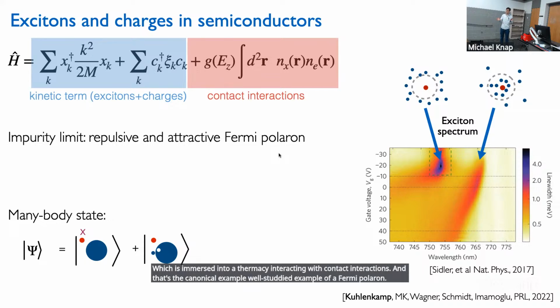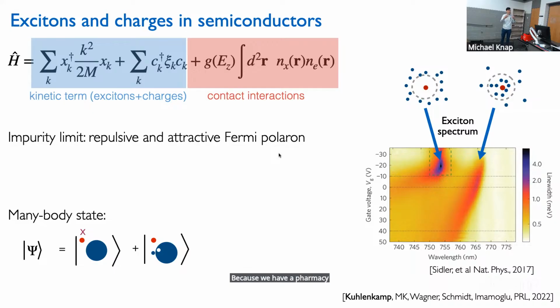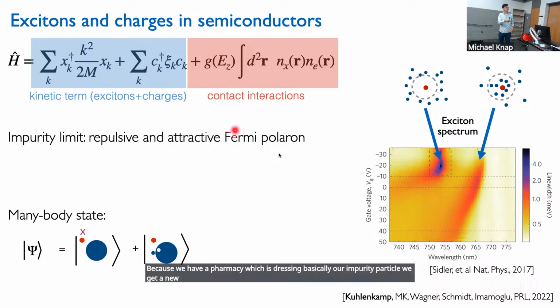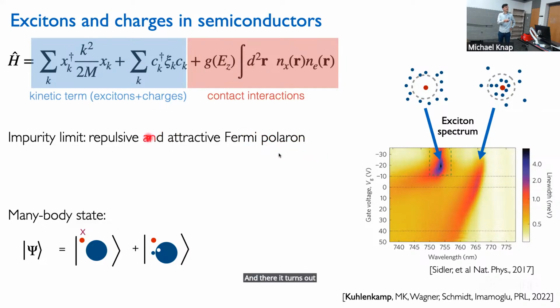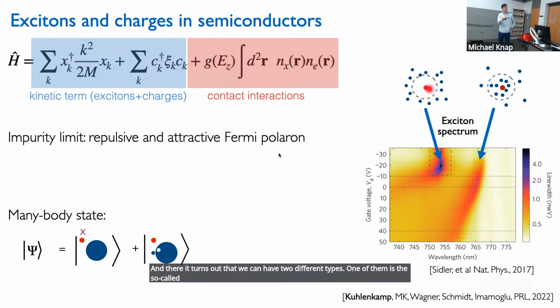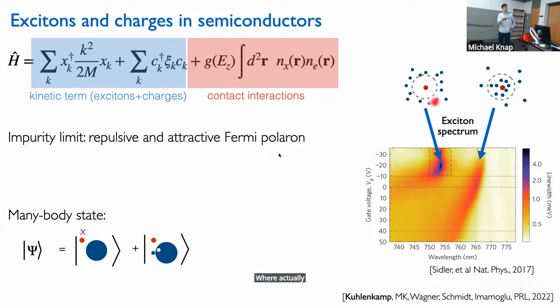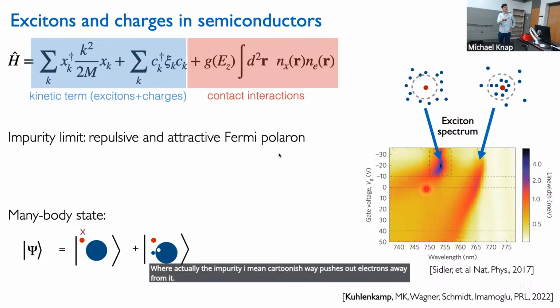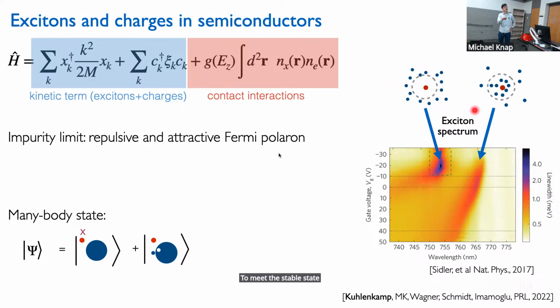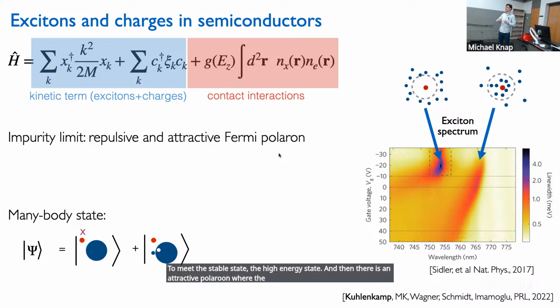Because we have a Fermi sea, which is dressing basically our impurity particle, we get a new quasi-particle, which is this so-called Fermi polaron. And there it turns out that we can have 2 different types. One of them is the so-called repulsive polaron, where actually the impurity, in a cartoonish way, pushes electrons away from it. It's a metastable state, a high energy state. And then there is an attractive polaron where the electrons are actually sucked in to the impurity.